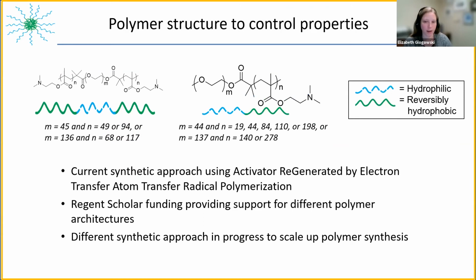So because we've filed the patent and with extreme help from WiSys, we can talk more about the polymer structure we've been looking at. So we've been looking at diblock and triblock copolymers. So by changing the architecture, we change the properties that we observe for these materials. So we've looked at a wide array of different polymer structures. Like I mentioned, both the diblock and the triblocks. The blue component is a fixed water-soluble block, and then the green piece is the part that's stimuli responsive. And so it will change properties in response to a change in pH and or temperature.